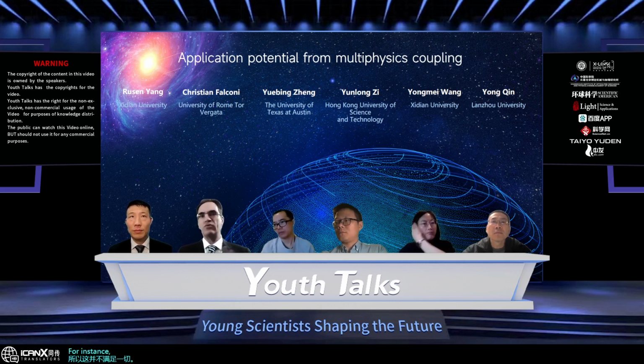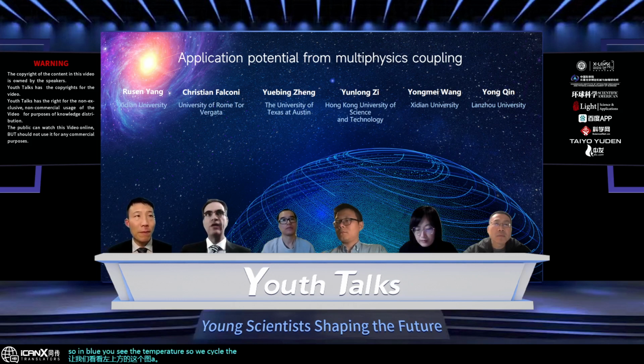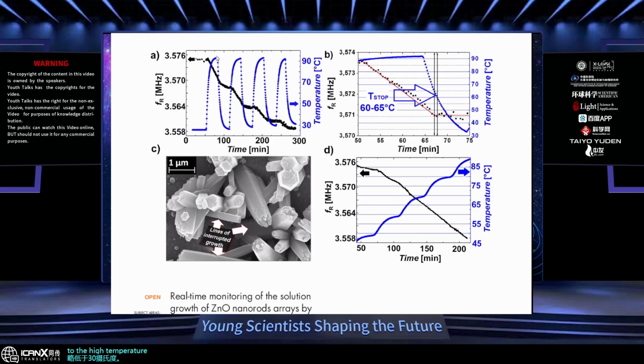For instance, just to give you an example, let's see this figure A at the top left. So in blue, you see the temperature. So we cycle the temperature from room temperature, slightly less than 30 degrees Celsius, to the high temperature required for promoting the growth of the zinc oxide nanowires in solution, so about 90 degrees Celsius. And then we bring the temperature back down, then back up, down. So temperature cycles. And here you see the resonant frequency of the quartz crystal microbalance.